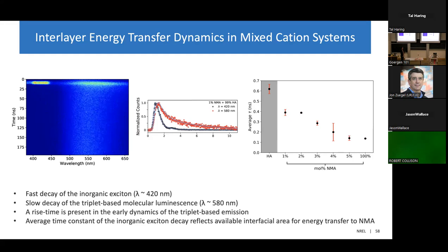And then finally, I calculated the average time constant associated with the inorganic exciton decay in this series of perovskites, and we see this nice trend where the hexylammonium has the highest average time constant. The pure naphthalene system has the shortest. And then the rest of the trend is reflecting the amount of interfacial area that is available for the energy transfer.